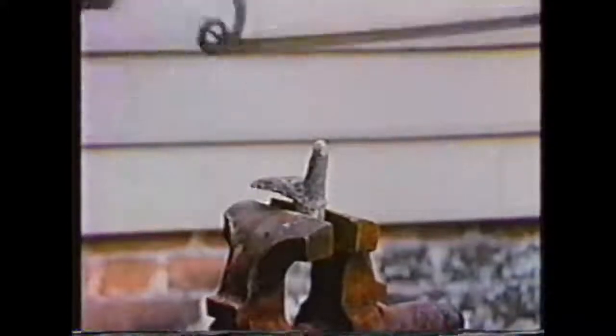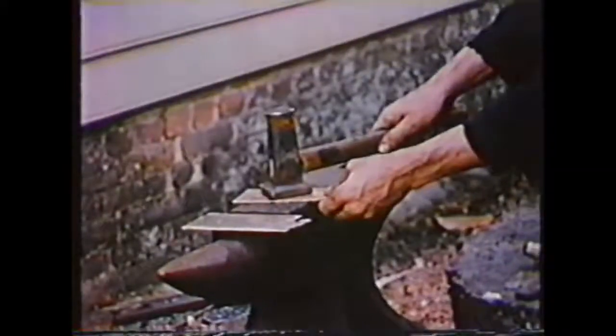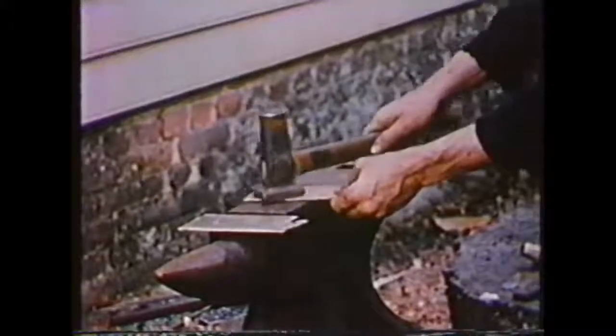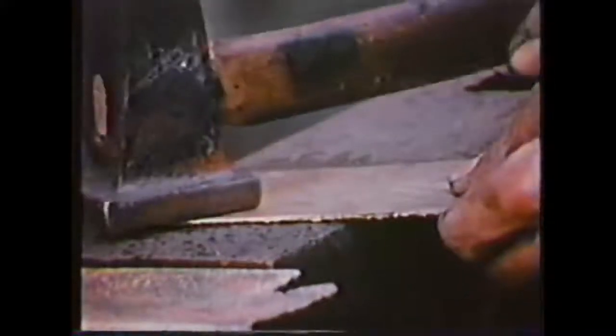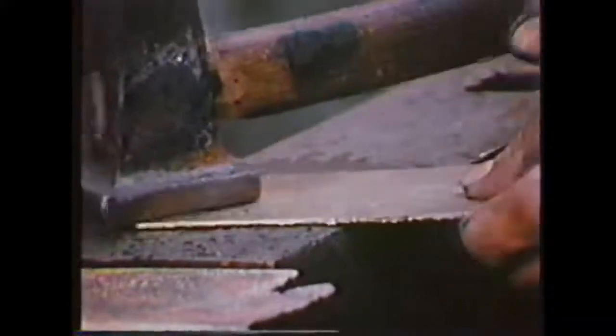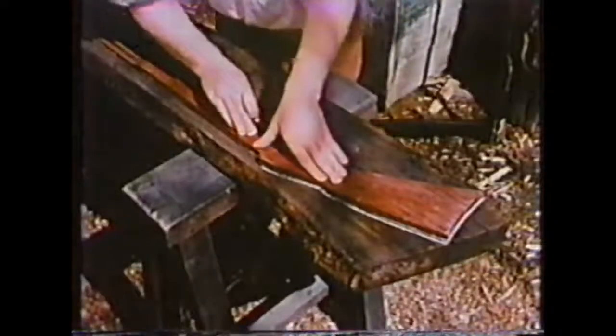Sheet brass is first cast into a flat ingot. Then it's hammered on the anvil with the flatter. The hammering makes the piece much tougher and of denser quality throughout. The brass hardens from hammering, so it is heated red hot and quenched in water to anneal it, and then hammered and annealed several more times.